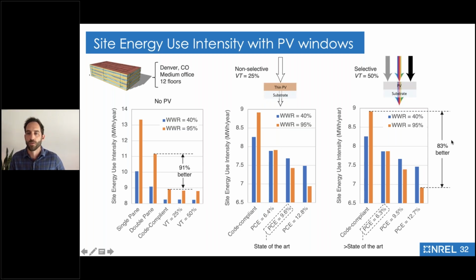No matter which technology you choose, you're seeing from code compliant windows, again, with the caveat of this high window to wall ratio, an 83% increase in performance going from a code compliant or low E window to a photovoltaic window that integrates also low E and all the thermal properties of these things. So by harnessing 12% of the sunlight in Denver, you actually do an 83% better job of having an energy efficient building. So I think this is really exciting. I think this is where photovoltaic glazing is going, that we can hopefully see a similar step change that we saw in the past, where low E really revolutionized the industry, and see a similar revolution based on photovoltaic glazing.